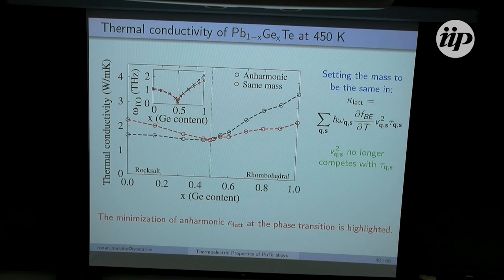And then finally, looking at the thermoconductivity, you see this red curve here, and the group velocities are no longer competing with our phonon lifetimes, so we get quite a nice reduction, starting from lead telluride, going towards the phase transition, and similarly, on the rhombohedral phase, getting a nice reduction, though it's perhaps not as obvious now because we've removed the reducing group velocities that have assisted the reduction in this case. But it does highlight the fact that our anharmonic thermoconductivity is minimized at the phase transition.